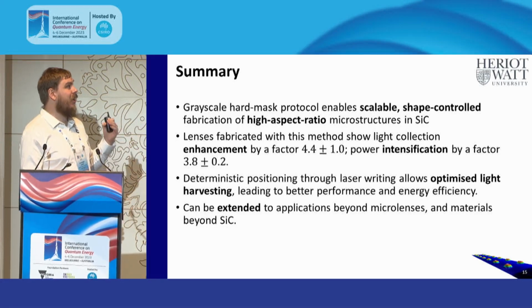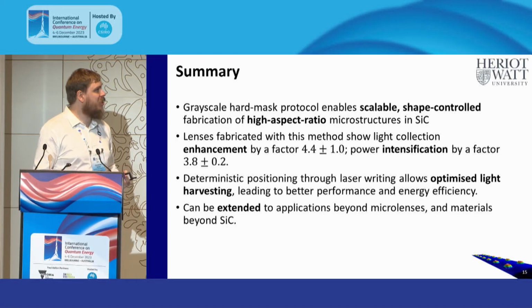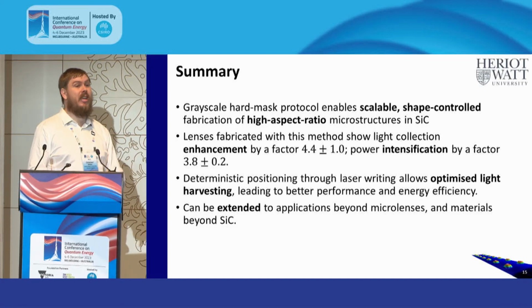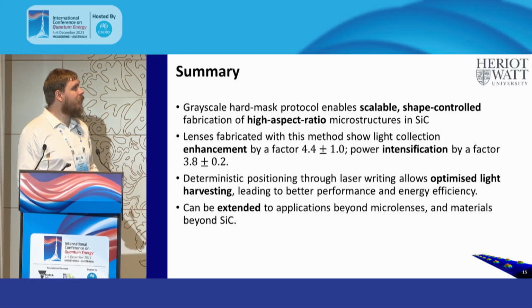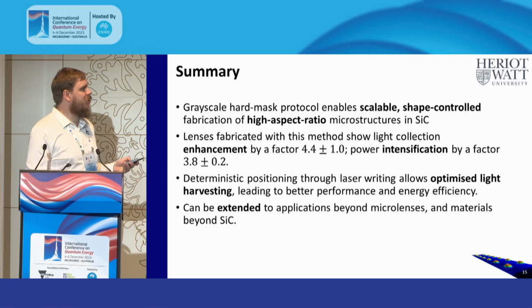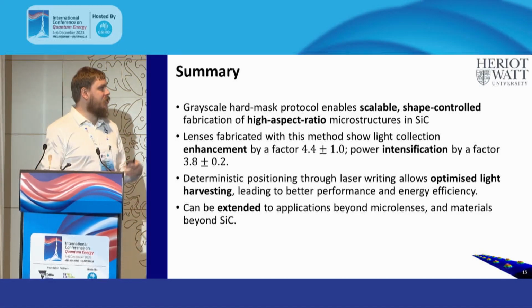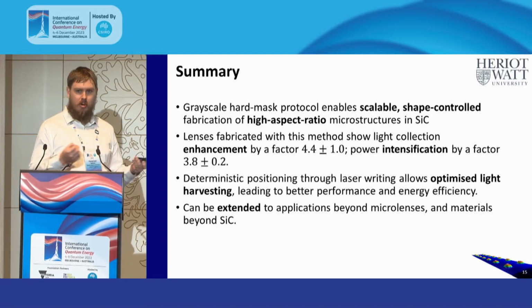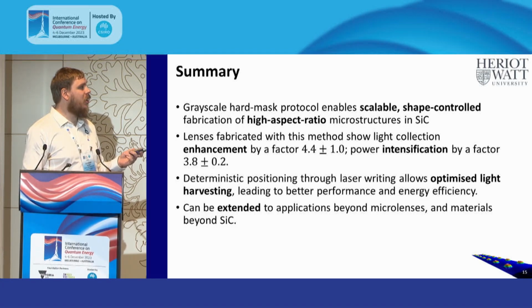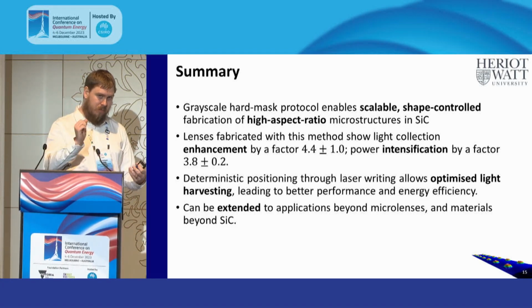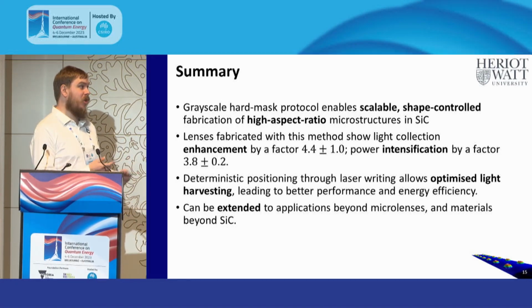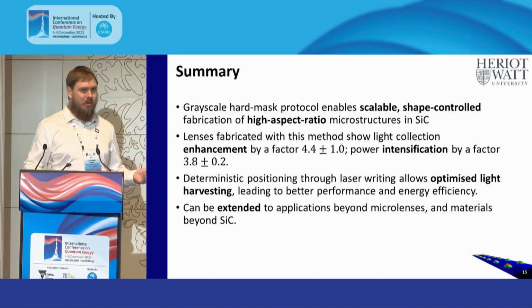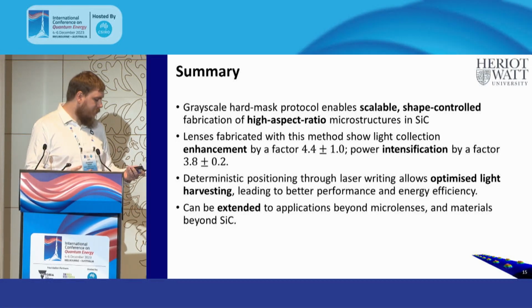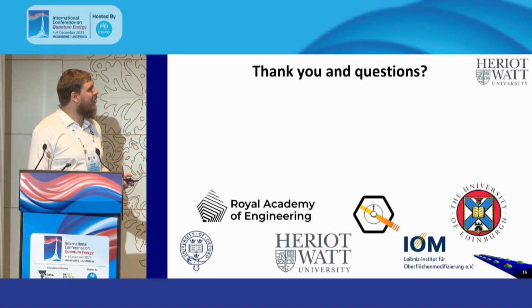Just a quick summary: the grayscale hard mask fabrication protocol I was presenting gives us a way to do scalable, shape controlled, and high aspect ratio microstructures in silicon carbide. Some initial lenses we fabricated with this method show enhancement of up to 4.4 in brightness and 3.8 intensification of the laser spot, and gives us a way to improve our performance. We're also working on optimizing the light harvesting by choosing where our emitters are. And we can extend this beyond microlenses and materials beyond silicon carbide. That's all exciting because we've got that process, but there's more work to be done. Thank you very much. Any questions?